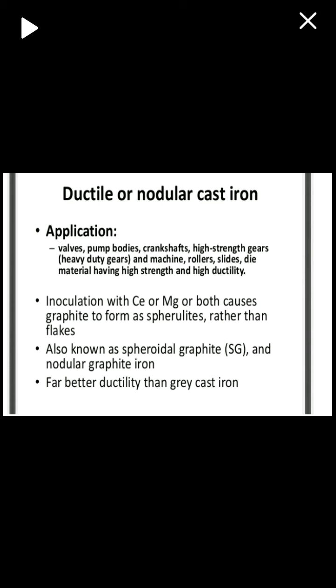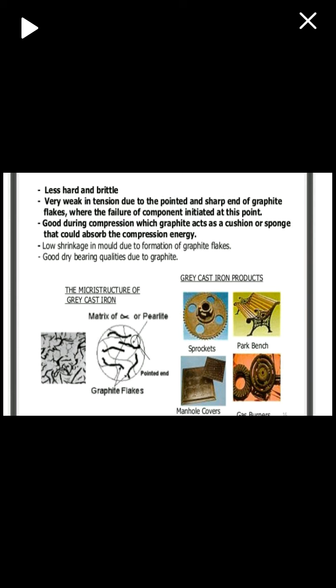and nodular graphite iron, far more ductile than grey cast iron, less hard and brittle. Grey cast iron is very weak in tension due to the pointed and sharp ends of graphite flakes, where failure of the component is initiated. Good during compression, where graphite acts as a cushion or sponge that could absorb the compression energy. Low shrinkage in mold due to formation of graphite flakes. Good dry bearing qualities due to graphite.